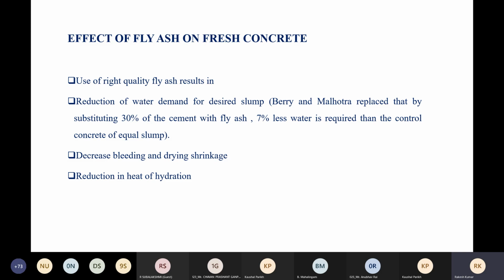Effect of fly ash on the fresh properties. What is the effect of fly ash on the fresh properties? First, if we use the right quantity of fly ash, it results in reduction of water demand for the desired slump. It is reported by Berry and Malhotra that if you replace 30% of cement with fly ash, there will be 7% less water requirement than in the control concrete for the equal slump.